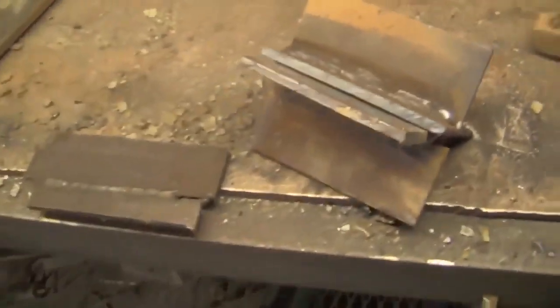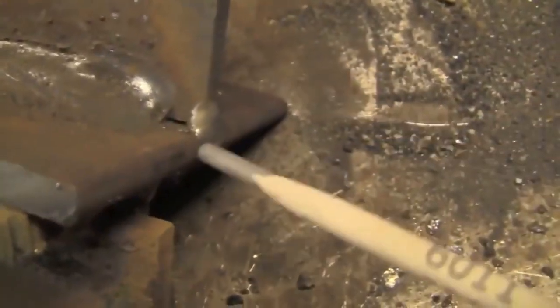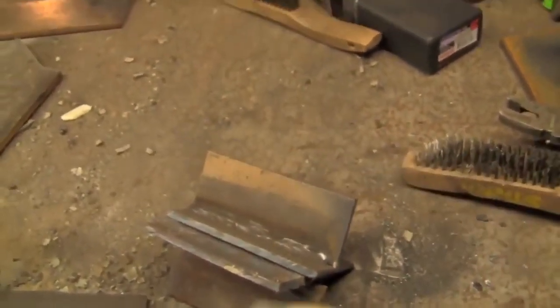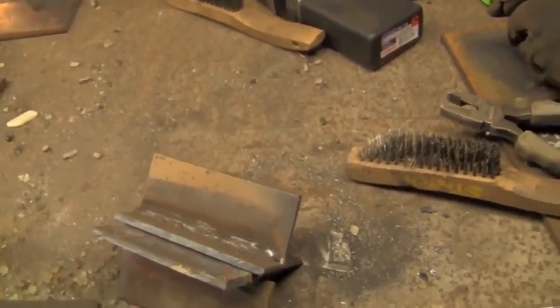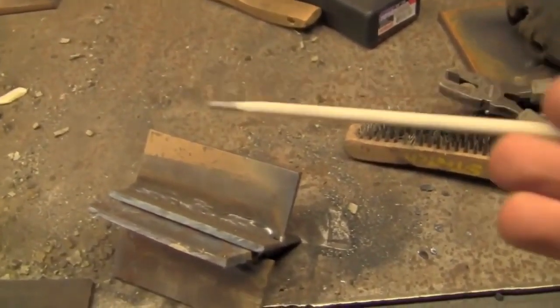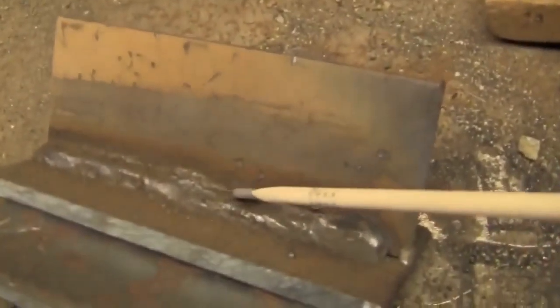And probably the most distinctive characteristic of too hot of a weld is what's known as undercut. It's when there's a little valley between here and the plate, when it kind of just digs in. And what causes that is too much heat. You melt the metal out of there, and no metal ever goes back, so you're left with kind of a valley up in here, most commonly on a flat position fillet weld. And so that is too hot of a weld.